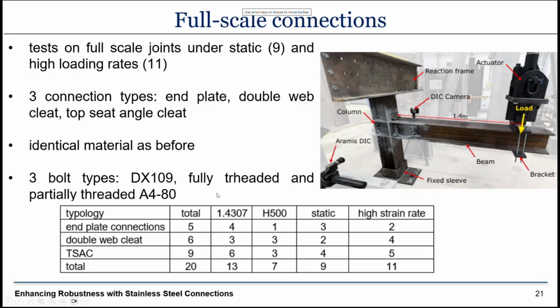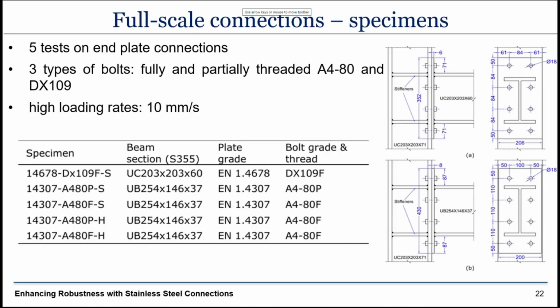and we can have a partially threaded bolt where you load it in tension, and instead of having failure in the thread region where you have a smaller cross-sectional area, you have failure in the shank region where you have a larger cross-sectional area, because the material there is weaker. You haven't strengthened it with the thread forming process.